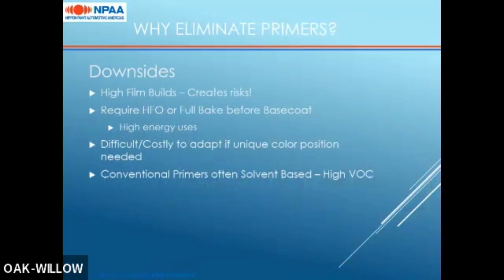So what are some of the benefits of eliminating the primer? The downsides of primers: typically they require high film build. This creates risks, particularly for popping and sag. They require HFO or full bake before base coat, which is a high energy use. They also are difficult and costly to adapt for unique color positions, at least in my experience.